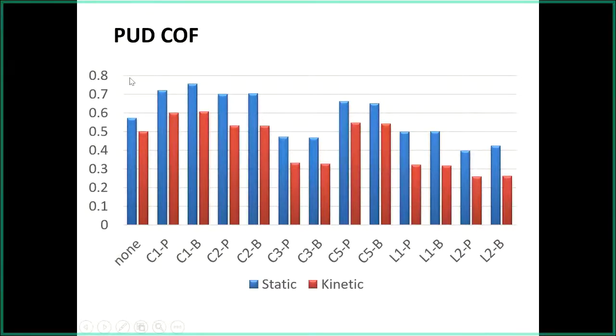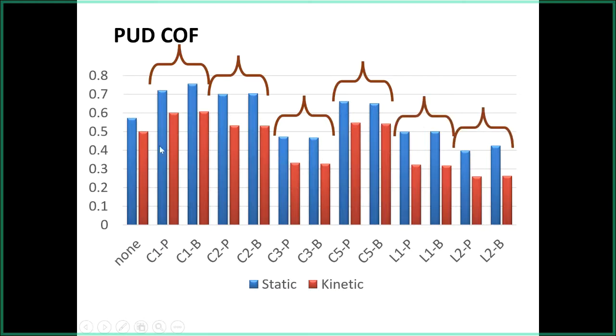A very sensitive test can be coefficient of friction. So just from those panels that I just showed you, we're looking at no additive, and then C1-B, and this is static and kinetic. The red bars, the kinetic coefficient of friction, tend to be much more sensitive. When you do coefficient of friction, for the static ones there tends to be a tackiness to the coating. So once it starts moving, that's where you get the more accurate number. So what you see here is in the C1 structure, the blue bars are very close, the red ones are identical. The same thing in C2, C3, C5, L1, and L2. So all of these are really performing identically on coefficient of friction.